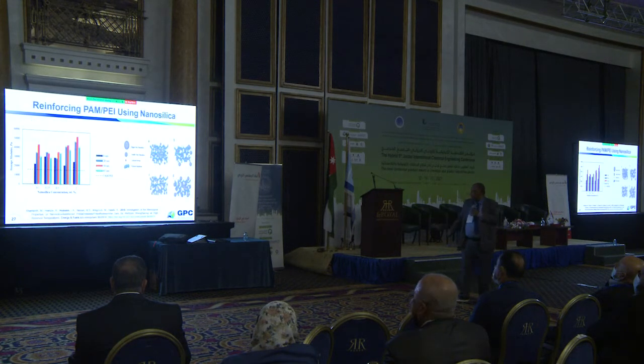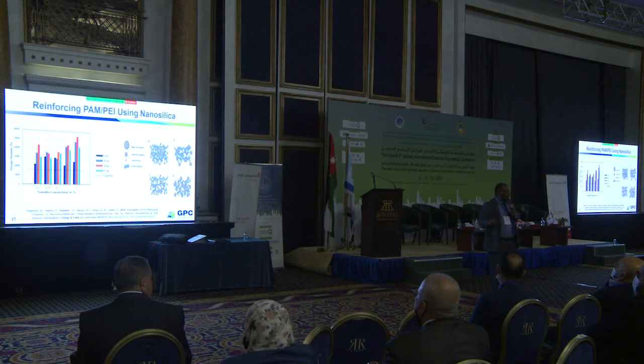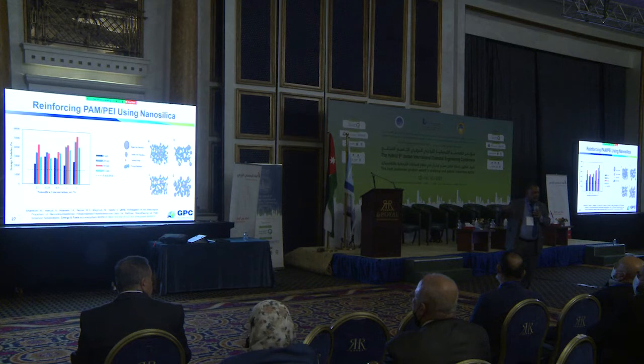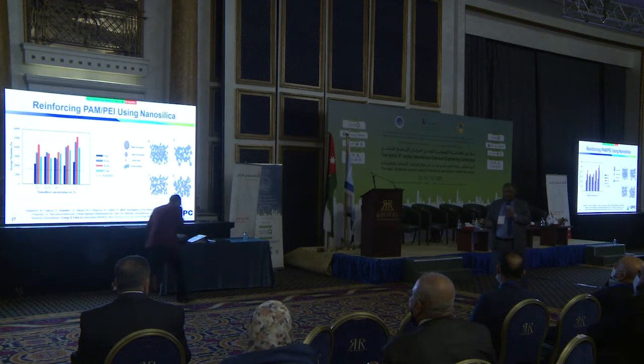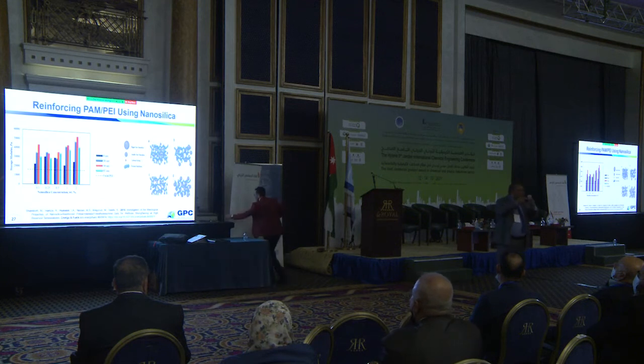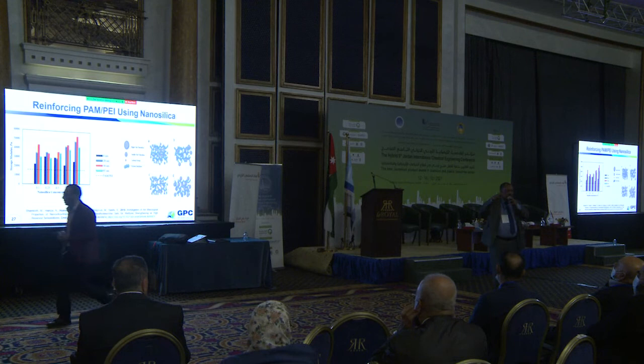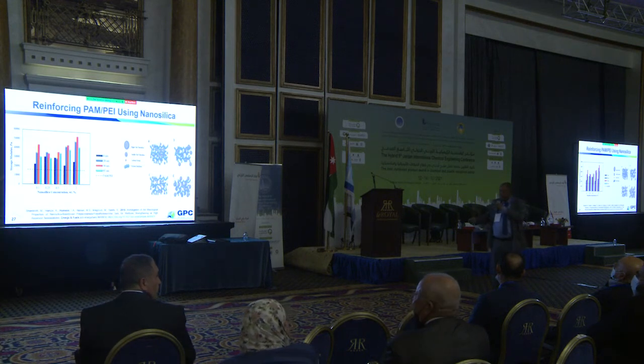It is applied later on; we need reinforcement. Polymer reinforcement is used a lot in polymer science. Now we also use reinforcement for the gel. We use silica by itself as well as silica functionalized with the cross-linker. So, functionalized silica as well as silica. And what we can see here is a major improvement when we use functionalized silica.